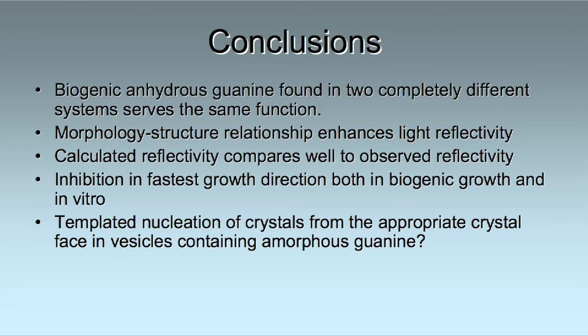So now to wrap it all up, we saw that both fish and spiders use the same material for the same function, but organize it in a very different way in order to optimize the reflectance of the crystals. The morphology structure relationship is controlled in such a manner that it enhances light reflectivity, resulting in reflectivity that compares well to the observed one. We saw inhibition of growth in the fastest growth direction, both in biogenic crystals and in vitro. And then the next question is, how do they do that?